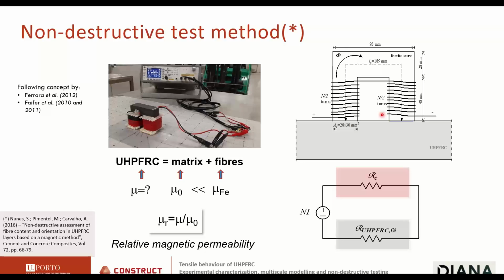So we developed a non-destructive test method following the concept previously introduced by other authors, Ferraro, Folfer, which is based on a U-shaped magnetic probe on which we induce a magnetic field. It's a good idea to use here the magnetic properties of the steel fibers, because if we measure the relative magnetic permeability of our material, we are sure that this is only related to the fibers. The relative magnetic permeability of the matrix is the same, for engineering purposes, as that of vacuum. No matter if you cast the element at 1 day, 2 hours, or 80 days, it's constant, always the same value. So any variation in the relative magnetic permeability is only related to the fibers.